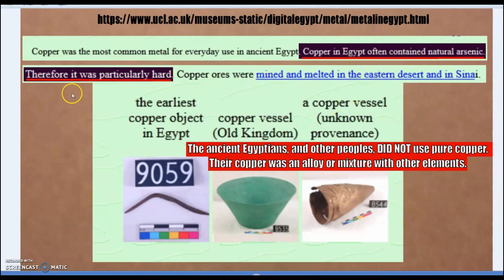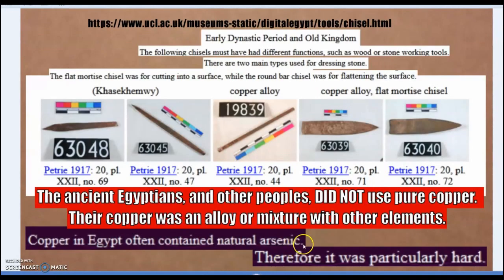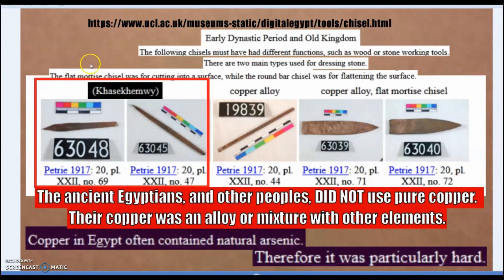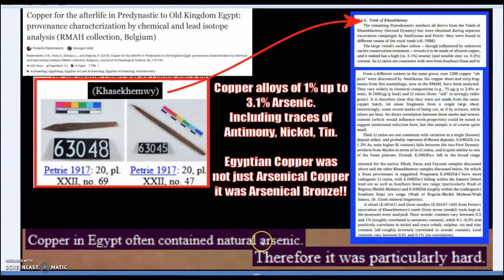Copper in Egypt often contained natural arsenic, therefore it was particularly hard. Again, the ancients did not use pure copper, not the way we think of pure copper now. It was natural arsenic, particularly hard. And let's look at Khasekhemwy. Here's a paper, Copper for the Afterlife in Pre-Dynastic to Old Kingdom Period. And I'll, of course, link these papers in the description. Here they link the tomb of Khasekhemwy and some of the artifacts found in there.